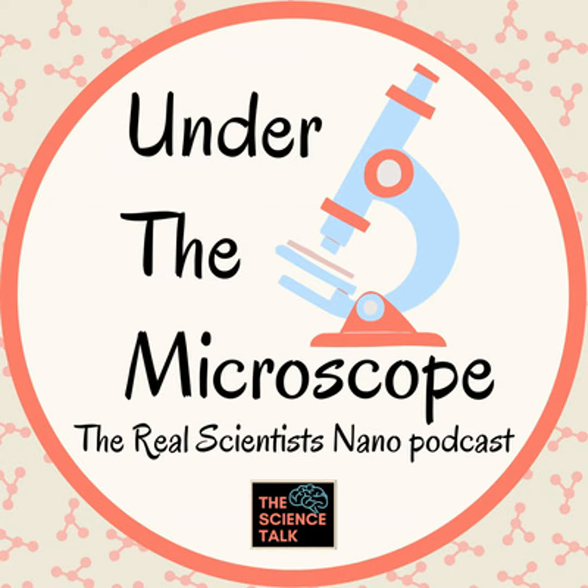The interesting thing is that to a large extent, it would keep that way because after growth is starting, it's sort of wetting the wire. And so it doesn't go to circular, at least not easily. But actually, I was looking at these tiny wires in the SEM, and what was even more interesting is that, you know, the best thing is that you find something that surprises you. Because I patterned these stripes in different crystalline orientations relative to the growth substrate, what I found is that in particular conditions where these stripes were aligned in a specific way to the crystal, the wires that grew actually had 8 facets rather than 6.